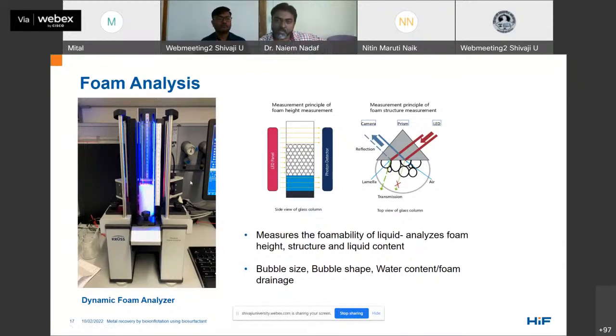So the foam needs to be stable as well as unstable depending on the stage of flotation. And again, as said earlier, the dynamic surface tension affects the foamability. So I would like to tell you how it affects in that way. So we saw that it affects the formation of bubbles when we measure the surface tension. So here again, it affects the generation of the bubble at the sparger by changing the average bubble diameter, which in turn affects various foam properties.